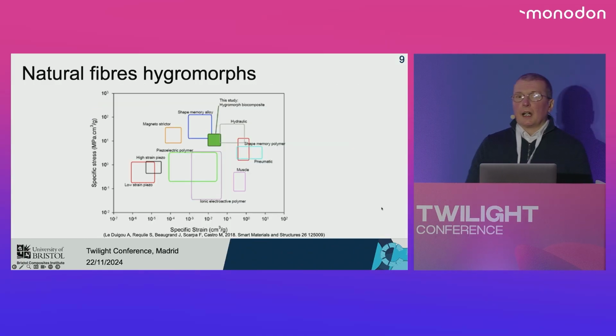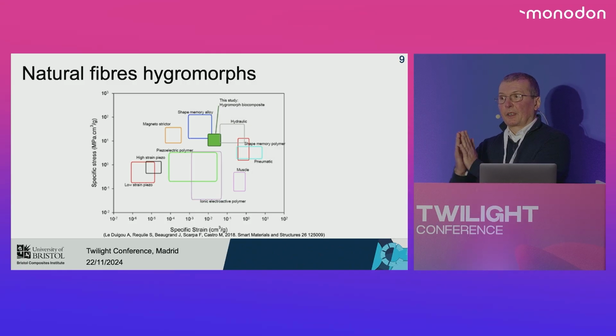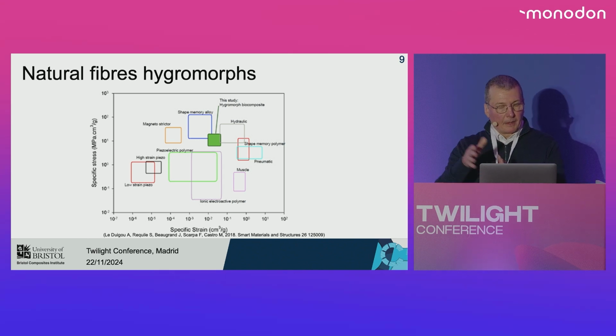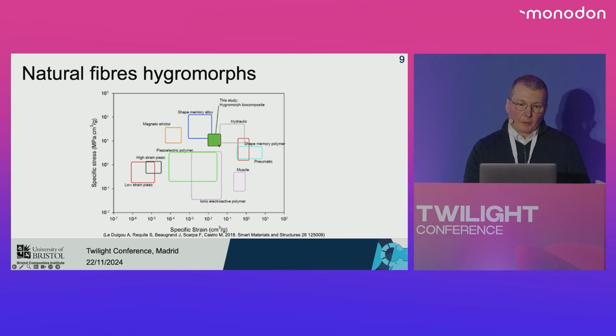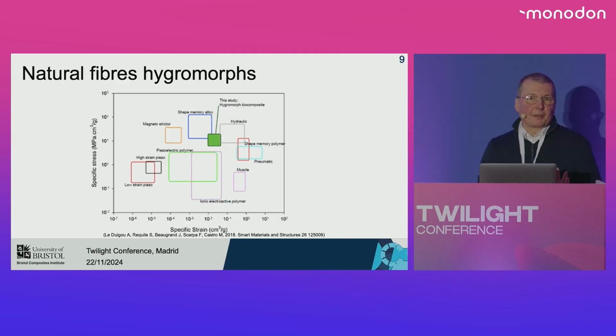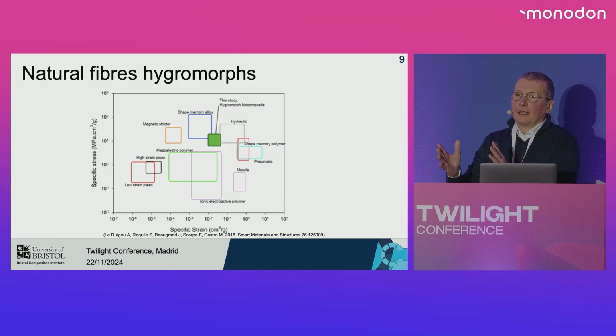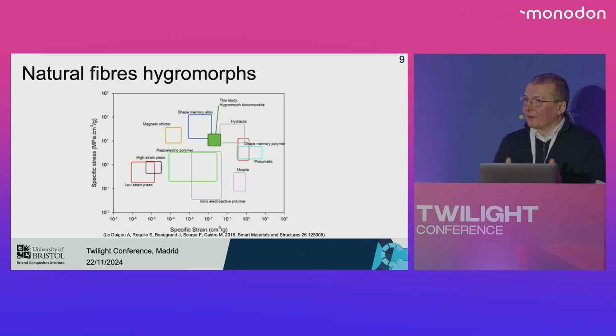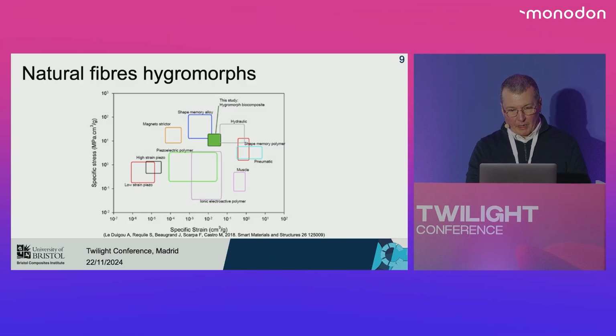And if you look at the actuation performance of these hygromorphs, this is quite interesting. If you plot the specific stress that provides the actuation authority, so maximum stress per density, versus the specific strain, so maximum strain per density that you can obtain, you will see that these types of composites sit nicely between shape memory alloys and hydraulics. From a certain point of view, they are surrogates or biomimicked units that are like really hydraulic pumps from a certain perspective. So in terms of actuation authority, these are quite interesting materials.